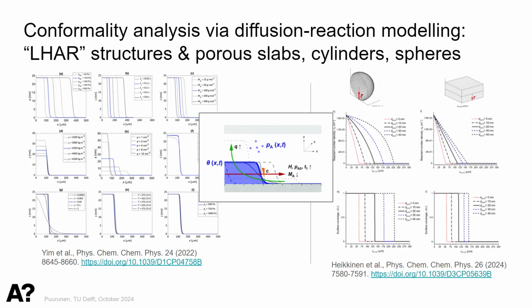These are very logical. And then when we are varying the growth per cycle, this is something that has not been so logical. Generally, people think that the higher the growth per cycle, the better, but actually we see here the opposite effect, that the higher the growth per cycle, the less the film penetrates. You could imagine that the surface is like a sticky mat, and it has a different density of sites that are bonding our metals. If it's a high growth per cycle, then that sticky mat has very dense sites. And if it's a smaller growth per cycle, then the sites are bigger and there are fewer of them. So when you throw balls on that, they will go deeper when the growth per cycle is smaller. I don't know if I can explain it well yet, but we observe it in simulations, and to me it's now logical, but I've heard people telling otherwise as well.